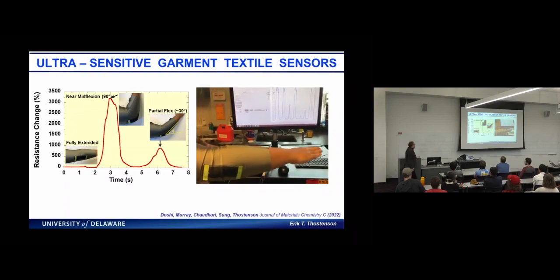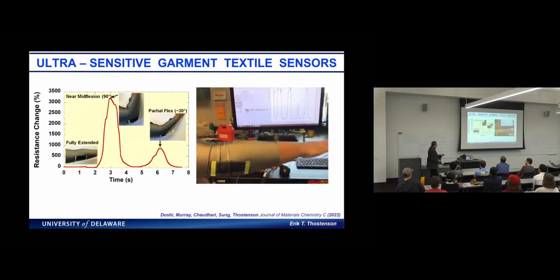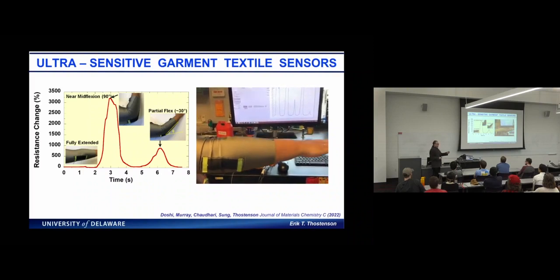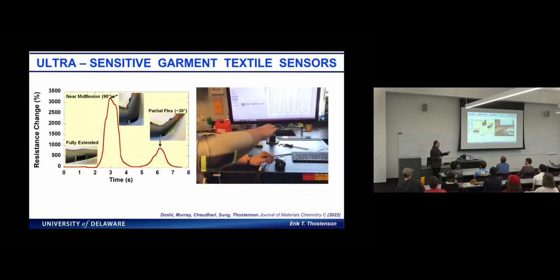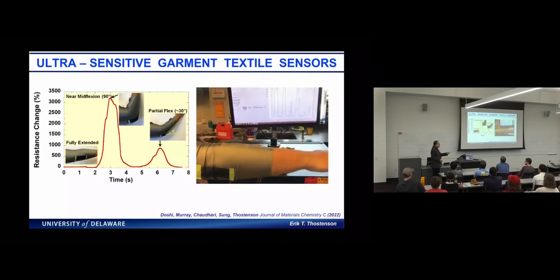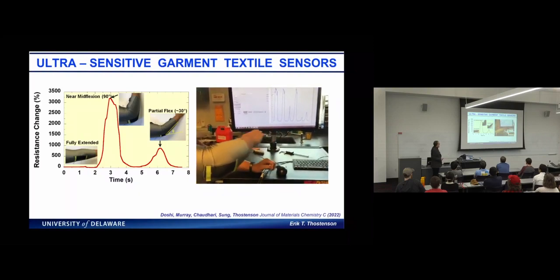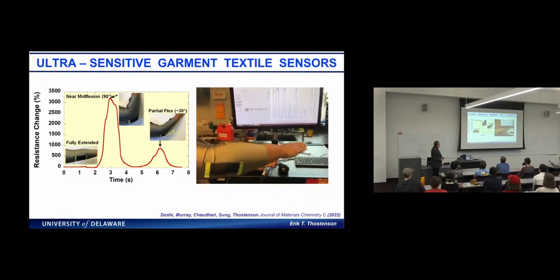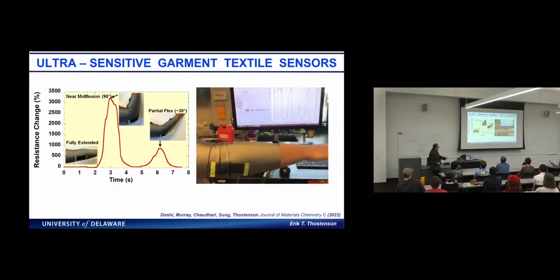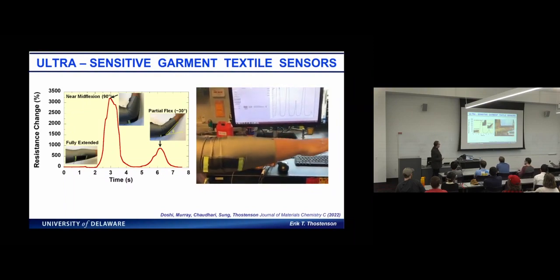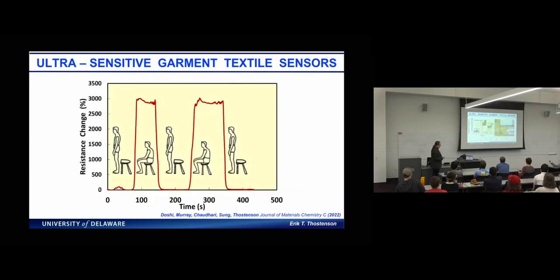And so this is a wearable garment, and this sensor, you wouldn't know that there's any coating. It's soft to the touch, it's breathable, and highly sensitive. It's actually that mechanism, a mechanism of deformation of the unit cell of the fabric, that gives rise to a really high resistance. And we've, of course, also done this on a knee sensor.